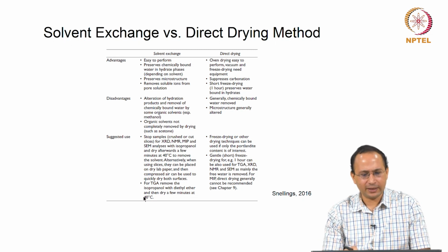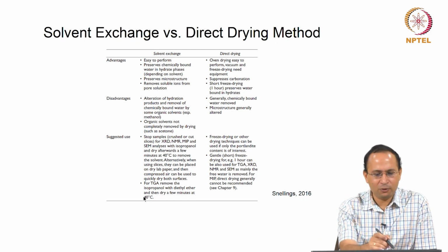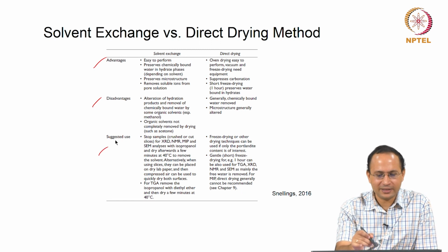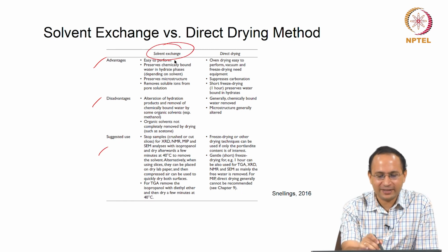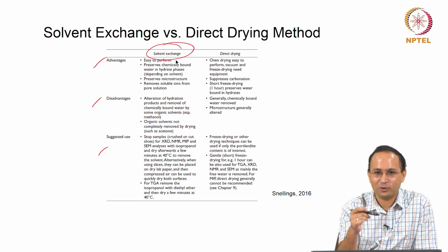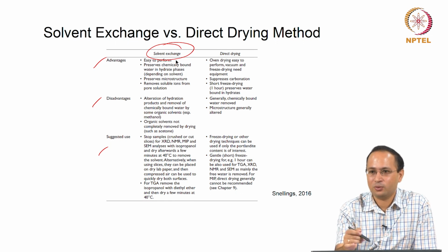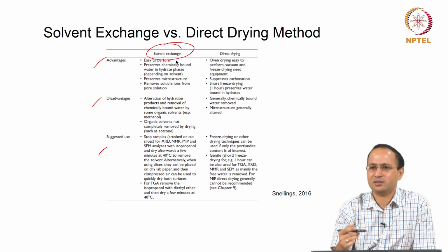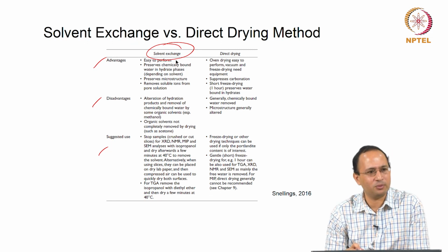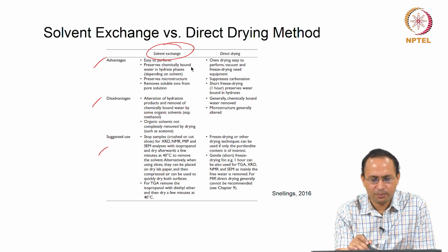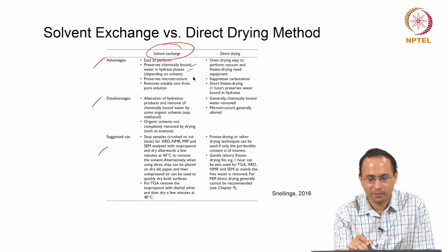So, here again are the advantages and disadvantages; you can go over the list, but let us see solvent exchange, right. It is easy to perform, you just have to submerge your sample in isopropanol or acetone. These days you most commonly use isopropanol, as acetone is harsher. It usually preserves chemically bound water, preserves microstructure, and removes soluble ions from the pore solution.